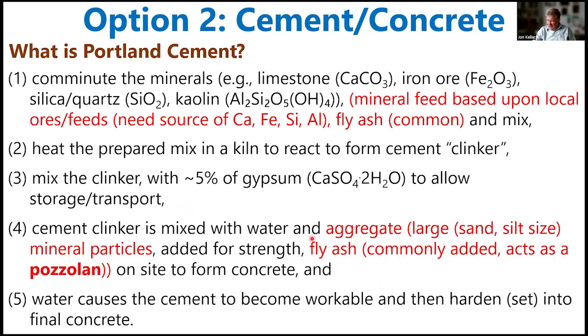Fly ash can also be added at that point when the cement is wet and being cured. And fly ash at that point is what we would call a pozzolan, a natural mineral that enhances the cement action. So there's a couple places where fly ash, or maybe tailings themselves, if they're of the right chemistry, could be part of the cement making process. Then the water's added, the cement becomes workable, and with that larger aggregate becomes concrete.